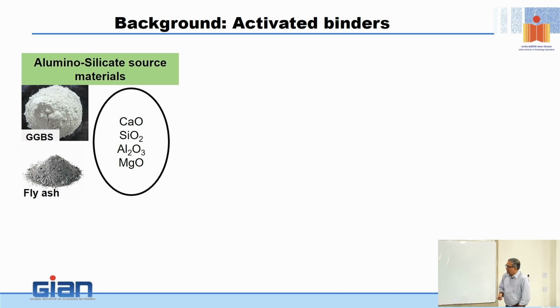So, first thing, what is an alkali activated binder? What I need is an aluminosilicate source, something that has alumina and silica in it. Usually we start with GGBS or fly ash. Sometimes even metakaolin is used. There are other silica sources too. These materials bring calcium oxide into the picture. Some do: GGBS contains calcium oxide, while fly ash is typically deficient in calcium oxide. But both typically contain silica and alumina, and that's what we're primarily looking at.